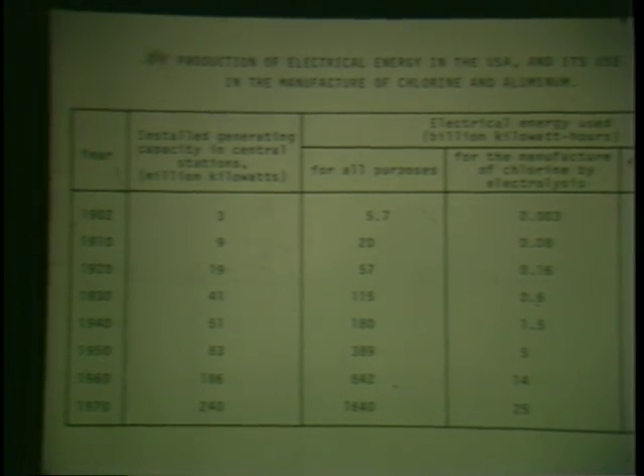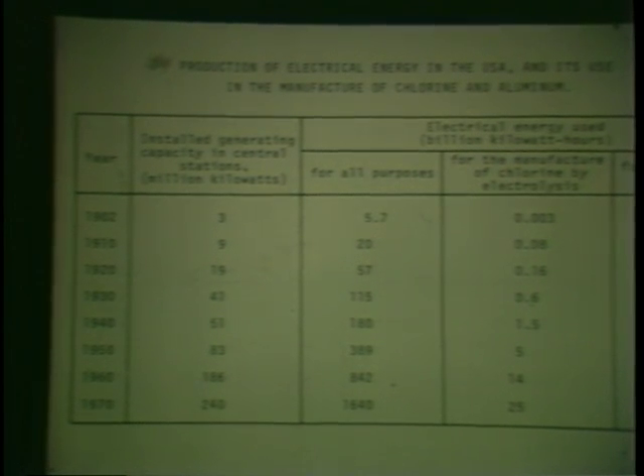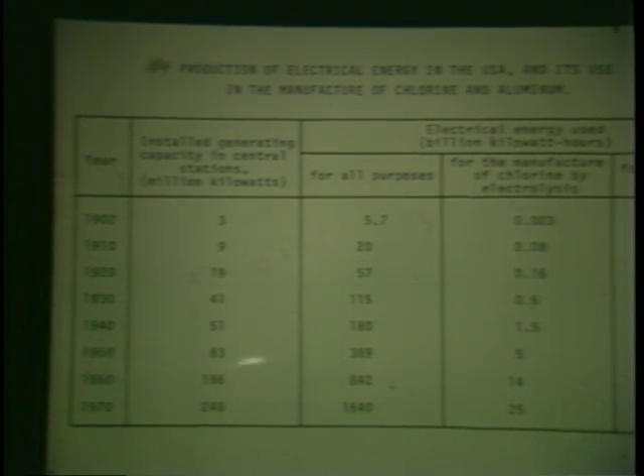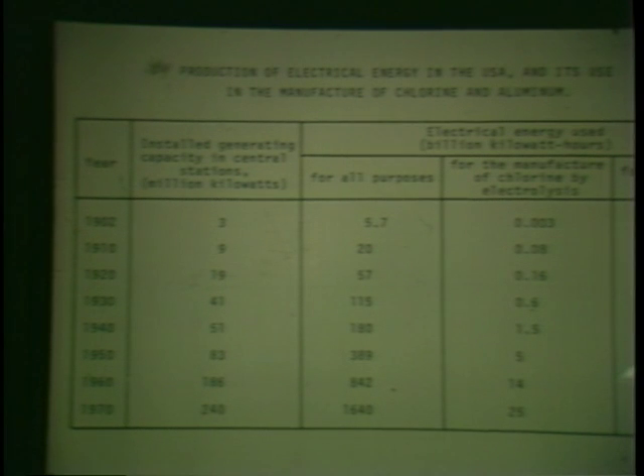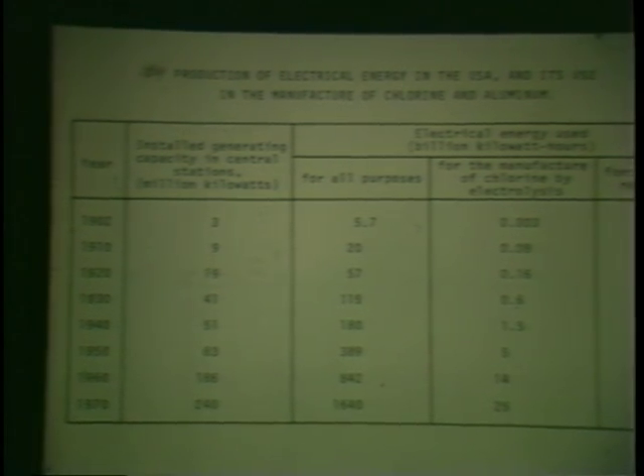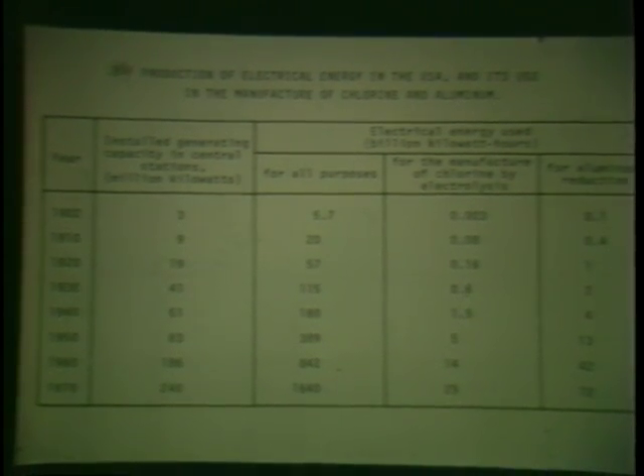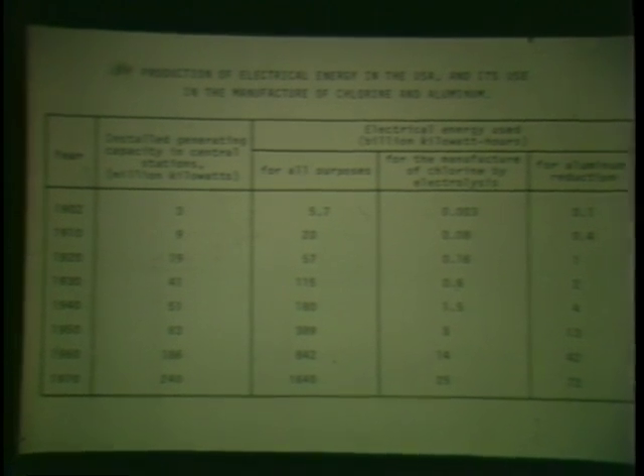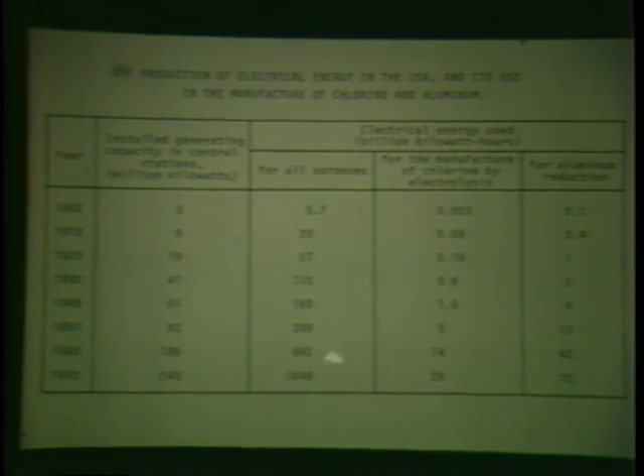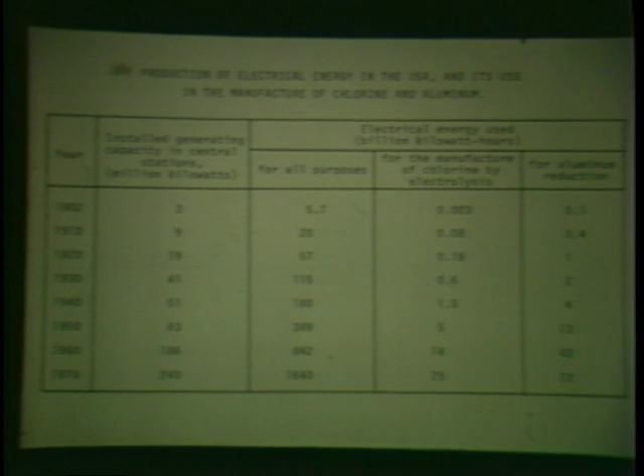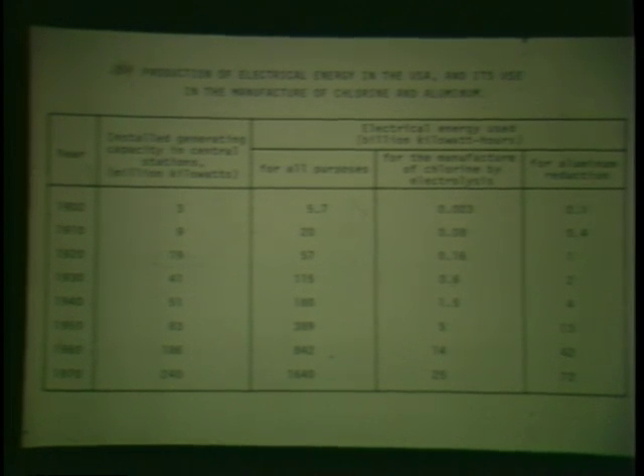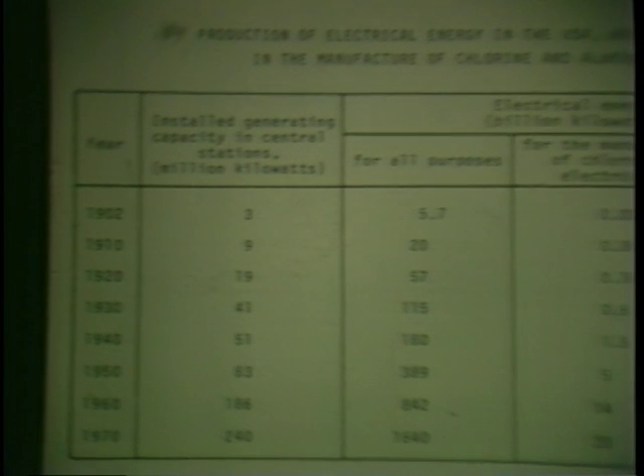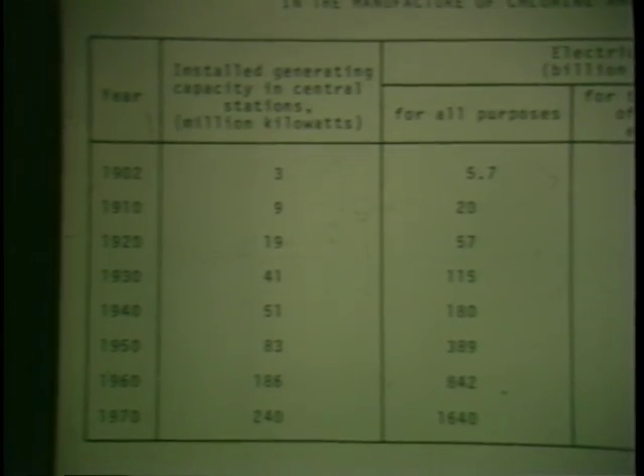In the beginning, 1 or 2% of total electrical energy was used for electrochemical purposes, but by the 60s, we were up to almost 7% just for aluminum and chlorine alone. Today, we are back to between 5 and 6% for chlorine and aluminum of the total, for all purposes, electrical energy generated, but well in excess of 10%, much closer to 15% for the industrially used electricity.